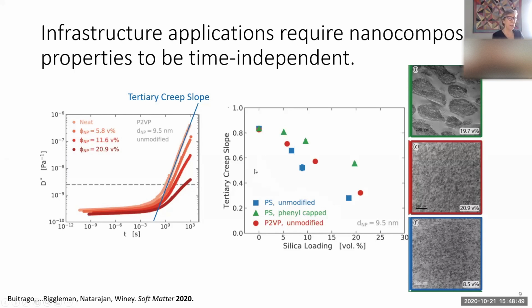And so you can see that this tertiary slope goes down as we put in more nanoparticles, and that's good because eventually we want this tertiary creep slope to be really flat, right? So we end up a very long time before failure. But in addition to the particle loading, we can start to see the importance of the particle distribution for these different examples. And then we need to worry about how the particle distribution evolves with time.